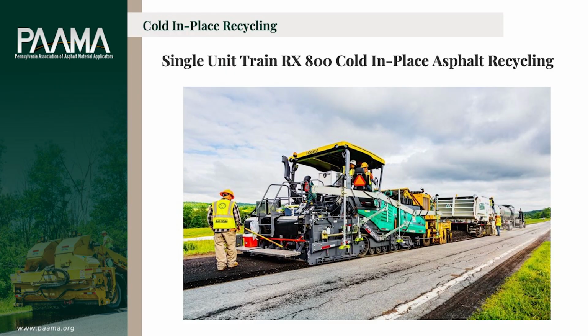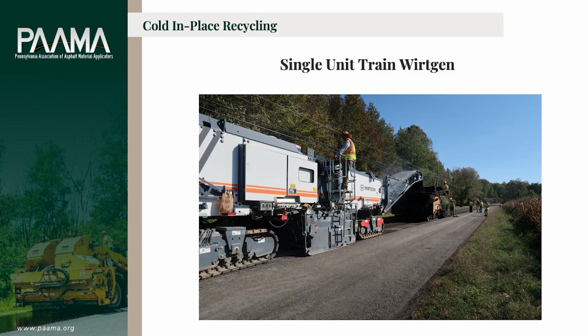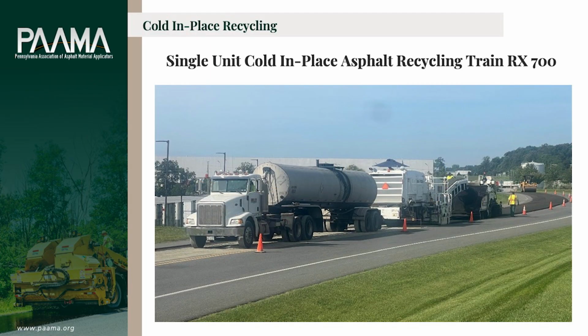The other type of machine, still a down-cut machine, is a two-unit train, so it'll have a first stage conveyor onto a second stage conveyor right into the paver. And the same with the single unit RX 700, which is a Roadtec machine. Same principle, asphalt tanker in front. The asphalt tanker is offloaded into the metering device on the front of the milling machine, and then that transfers the asphalt at the prescribed amount per square yard into the milling chamber, mixes it in there with the Portland cement and the road materials, and then directly into a paver where it's struck off. There's another shot of that RX 700.